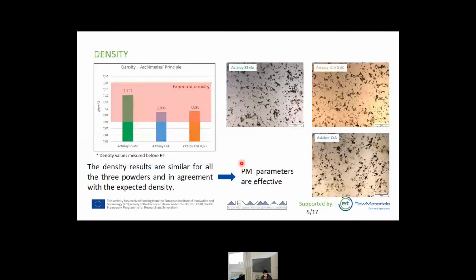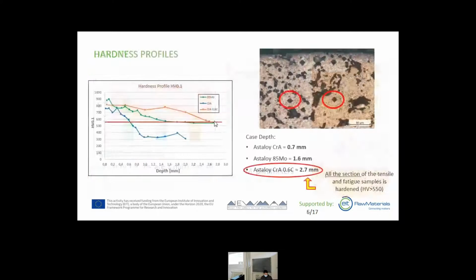Moving to the experimental activities, the first analysis was the density measurement, and the density results are similar for all three powders and in line with the expected density recommended by Hoganas. And we can say that the process parameters used for these three powders are effective, looking at the density measurement.